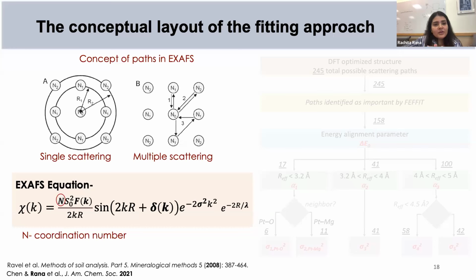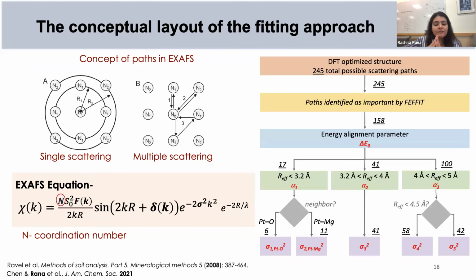So the conceptual layout of how the fitting approach is different in QuantEXAFS is that you really want to account for not just the single scattering path, but also the multiple scattering paths. So if you have a DFT structure and you start generating the model of it, once the scattering paths are generated, you take all those paths without any elimination, and then you have this parameterization scheme, which enables you to use all the paths and then model an EXAFS